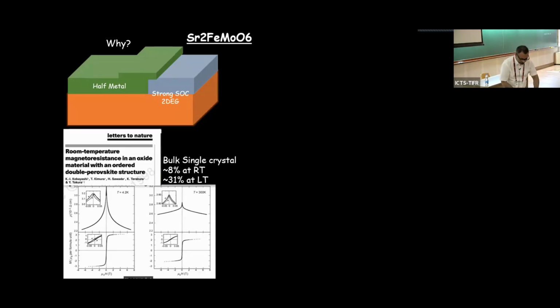Then we measured the resistivity at both parts. This masked part is always insulating. So at least detectable oxygen vacancy we have never found in terms of transport measurement. But in terms of the balance of the transition metal, of course it takes transition metal or any metal, like whatever, it all gets changed. Yes, physics must be, definitely. Because, Tanushree, you can see that you need a very small deviation from the 50-50, kind of 0.1% deviation from the 50-50 gives rise to the conducting state.